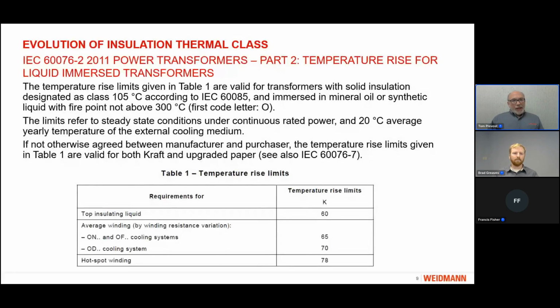If we switch over to the IEC standards, we can see a different concept of the value of thermal upgrading. The last time the main standard that defines a thermal class for transformers was revised was in 2011. In fact, this is being revised as we speak right now, but the current standard states that there's only one value for temperature rise limits. And in fact, it says, if not otherwise agreed between manufacturer and purchaser, the temperature rise limits given in Table 1 are valid for both kraft and upgraded paper.